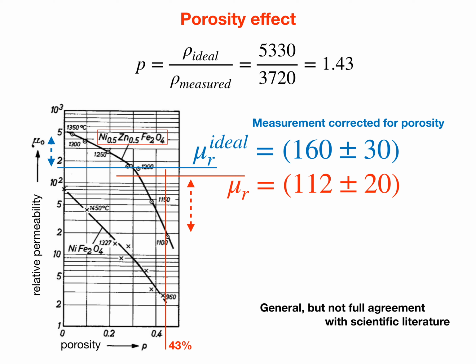Adjusting the measured relative permeability of 112 for this effect gives the result of 160 with an upper margin of error of 30. Both values agree generally with the literature values shown in the diagram on the left. However, good agreement is not achieved. Since permeability also depends on the grain size of the polycrystalline material, the remaining discrepancies could be due to that.